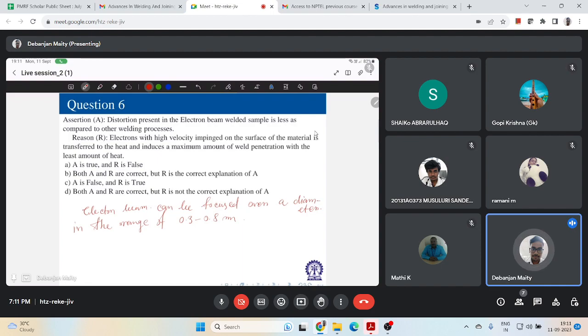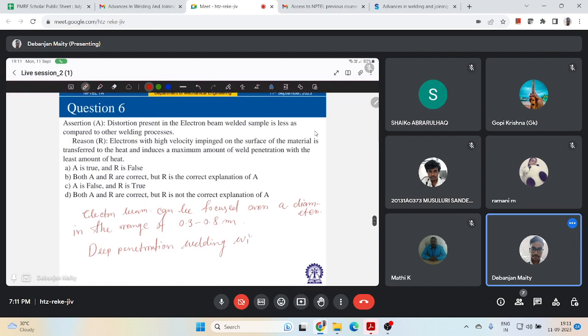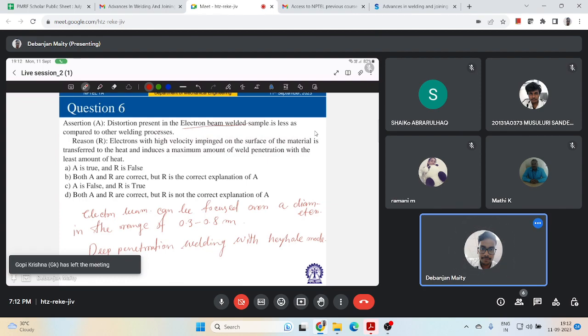And the key feature is its ability to perform this deep penetration welding with keyhole mode. Here it says that distortion presence in the electron beam welding sample is less as compared to the other welding process. Yes, this is true. Why? Because the electrons with high velocity impinged on the surface of the material is transferred to the heat and induces a maximum amount of weld penetration with the less amount of heat. This is also true, and this is the correct explanation. So B is my correct statement.